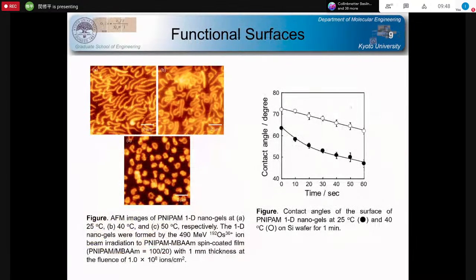But more interestingly, once the nanowires are isolated and we heat up the substrate, the nanowire shrinks, as shown in this viewgraph. And once we cool down to below the phase transition temperature, the nanowire stretches again. Such morphological changes were clearly observed with a simple temperature control. So we have successfully realized a thermal-responsive one-dimensional nanowire system based on these very well-known, commercially available polymeric systems.